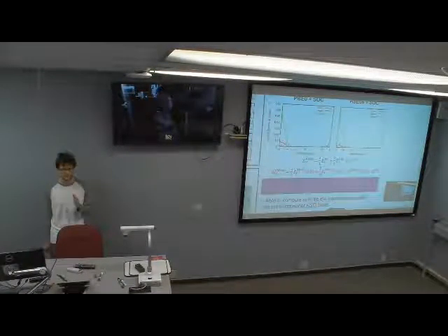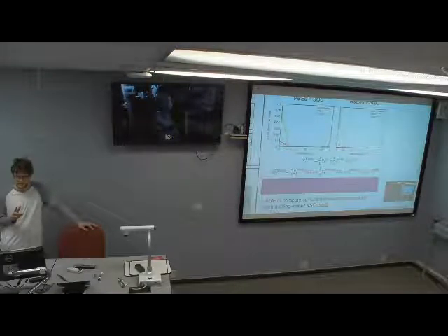While with the HSE06, which isn't fully done yet, but only needs a couple more steps to converge, you can see that I didn't multiply the doping states, but there is a hybridized doping state within the gap. And it's hard to see, but in the valence band, the doping states are hybridized with like LUMO+3, LUMO+4. So it's not too far from the band edge. So it seems like functionals which include more HSE character describe these systems better. I'm not sure exactly why, because I'm not sure of the technical differences between all of them. I know they include different amounts of the Hartree-Fock exchange and some other different parameters, but I'm not exactly sure why the HSE works better than PBE0.